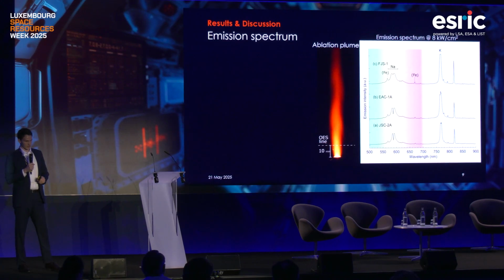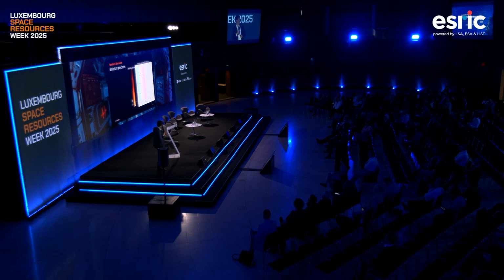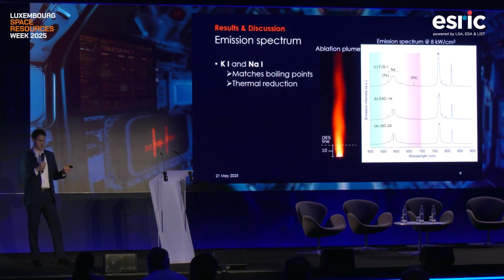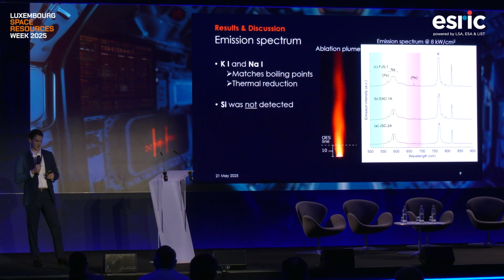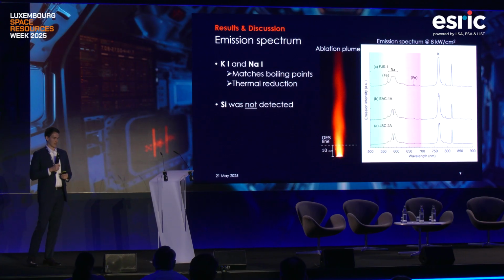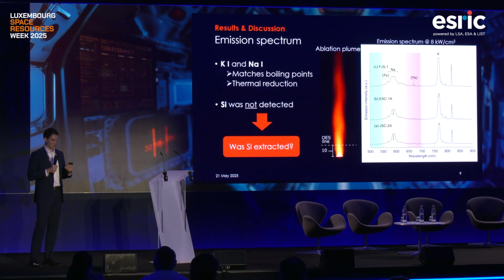We see mostly sodium and potassium present, strongly radiating in this spectrum, and also lots of smaller peaks that were not all identified, some of which we believe to be iron. But most importantly, potassium and sodium match with the boiling points, and moreover, they are obviously thermally reduced if they were present as an oxide before. However, what we did not see is silicon. We saw earlier we exceeded the boiling point of silicon dioxide. However, silicon was not detected in the spectrum. But still, the question remains, was it extracted or not?